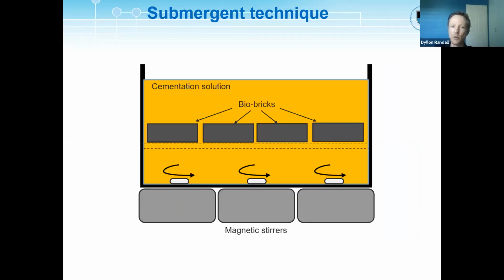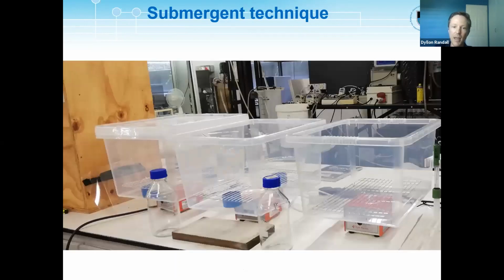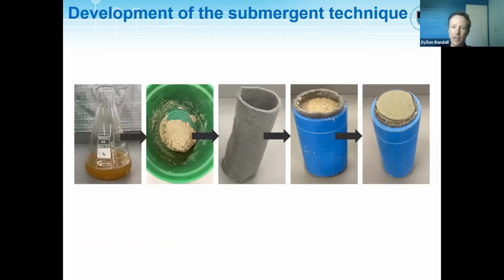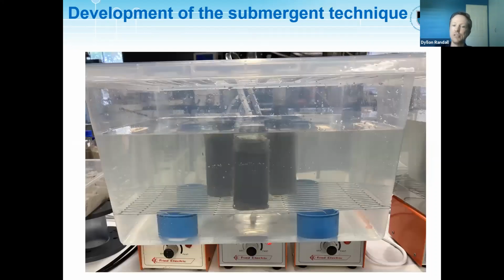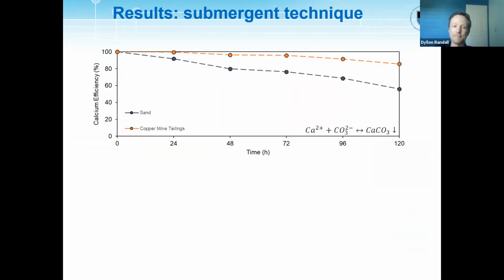And then we moved on to what we call a submergent technique. So essentially we take molds of permeable material, so geotextile in this case, make a shape of a brick, and submerge it in our cementation solution, which would be a combination of our urine and our calcium. And so this is what the system looks like. And we started with making columns simply because we could make a lot of them and then really understand what is happening with the process. So this is what it looks like when you simply just have the columns submerged in your cementation media.